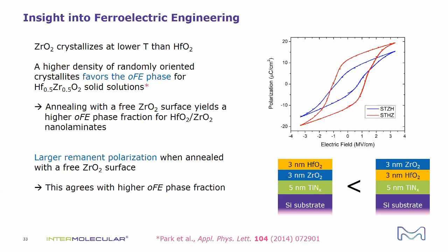But it also turns out that there are some cases where the thermal disorder parameters don't have a fairly straightforward relationship from one to the other. So there's some evidence that in some phases of zirconium oxide and hafnium oxide, for example, some disorder parameters are much larger than others within what we might consider to be the same coordination shell. So I think there's a lot of different ways to do it. We just picked a way that was simple and straightforward and ended up giving us really good quantitative agreement with experiment, but I'd love to hear and see other ways to do it.